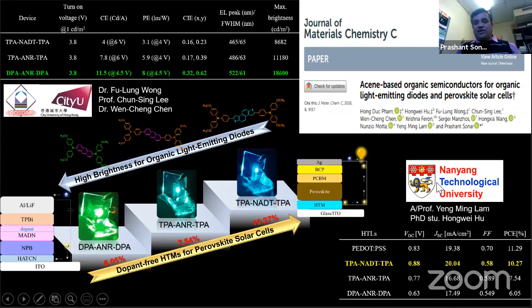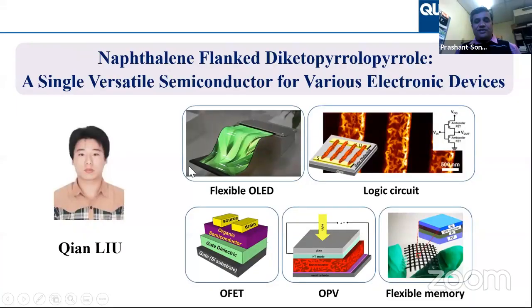And the same material we utilize as a hole transporting material. So it is a dual benefit: the same material can be used as a hole transporter as well as an emitter. And that's what we got in JMCC, where we demonstrated both types of devices. Efficiency wise, they are not that high. The highest one we can get is 10.27, but we also demonstrated it in OLED, and that was the reason. So it's some sort of versatile nature of some of the molecules, where we can make multifunctional devices.